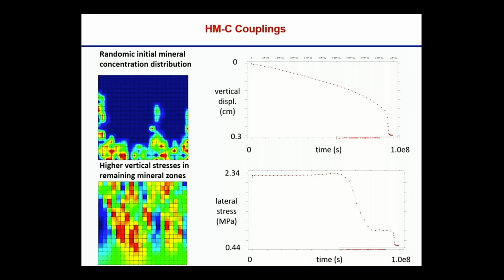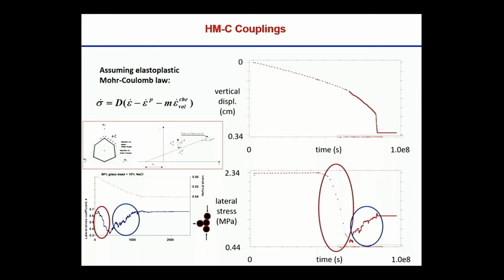But we would like to increase the stresses due to dilation. So we incorporate a very simple Mohr-Coulomb model. So the stress path goes through the Mohr-Coulomb envelope, and we have some plastic irreversible deformation due to this stress path. So we could capture the increase of the stresses, of the lateral stress, due to this rearrangement, that's an elastoplastic effect. But not enough to reach the initial lateral stress as in the test.